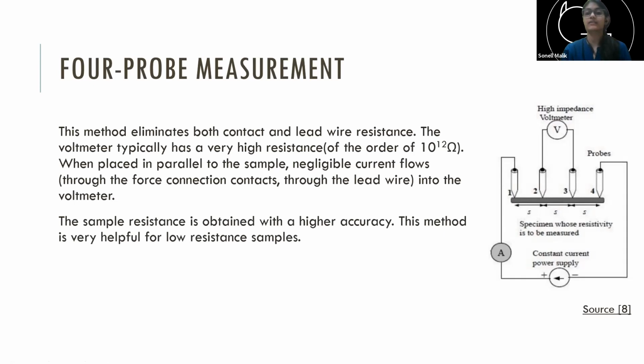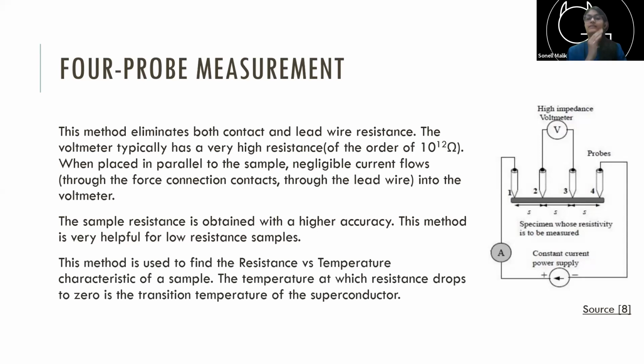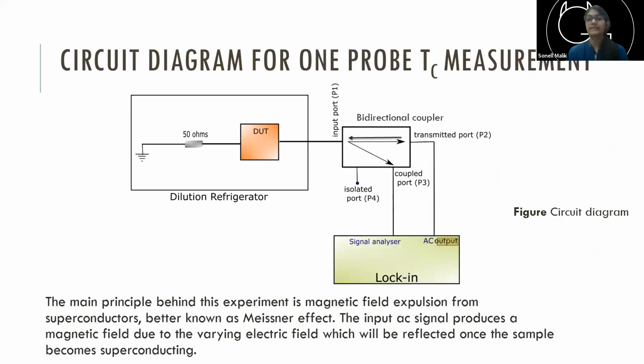So yes, you get high accuracy, and especially when we talk about superconductors, where we want to see if there is indeed zero resistance or not. For those cases, four-probe measurement is the only way to find the resistance versus temperature characteristic of any sample, which is how people find the transition temperature of superconductors. They make an RT curve, and the temperature at which resistance drops to zero is the transition temperature. So that is the four-probe method of doing it. What I did in my experiment, in my thesis, was a one-probe transition temperature measurement.